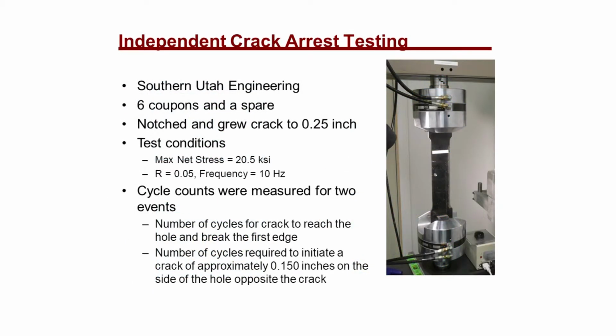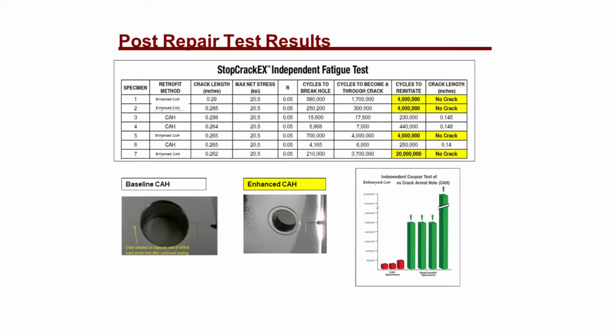Okay, we then did lab testing. We had both lab testing internally, but we also had some external lab testing. Southern Utah Engineering, 6 coupons with a spare, and basically it was cutting a notch, putting it in the MTS frame, and running it until you got a crack. And then we were looking for two different events. We wanted to see when the crack reached the hole and then how many cycles it would take to reinitiate on the other side. So the results were pretty astounding.